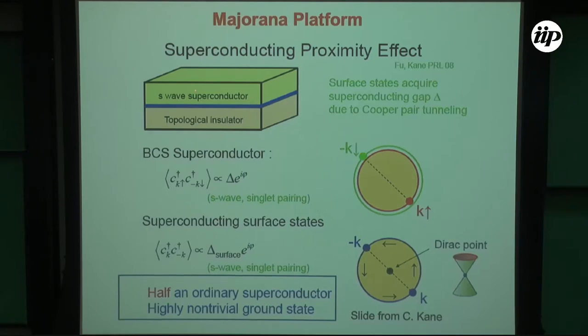So now we can see that to know experimentally whether we have a topological superconductor or not, what do we have to do? You can already see from this slide that we have to see at the interface, is there a Dirac cone like this that I already showed yesterday, right? There's a Dirac cone with spin-momentum locking. What I did not show is whether, if you attach a superconductor and cool below the transition temperature, there is Cooper pairing on the Dirac helical states, okay? But spectroscopically, we can do that. There is no problem. And that is our diagnostic that you are approaching a topological superconductor.